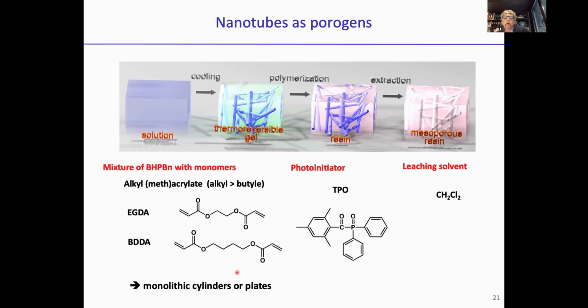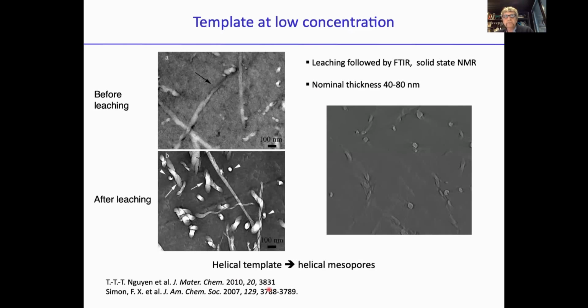So we can make small plates, small cylinders. Of course, what is limiting the size or the thickness is that, because we're doing photopolymerization, we have a depth of penetration of the UV. And these resins, we cut them in micro slices with an ultramicrotome. And we got very thin slices that can be observed directly under the microscope beam.